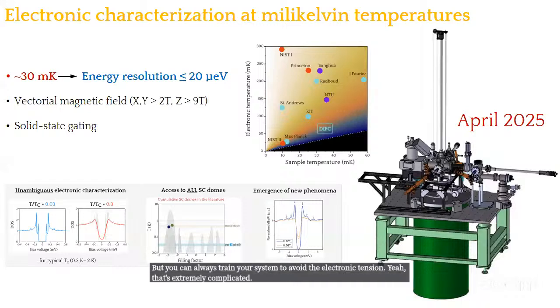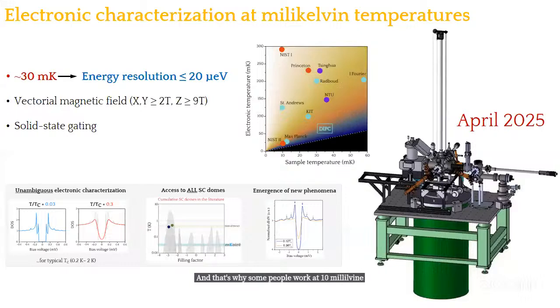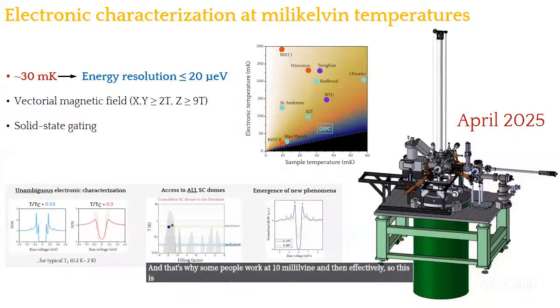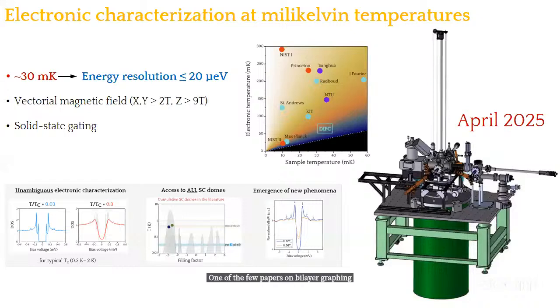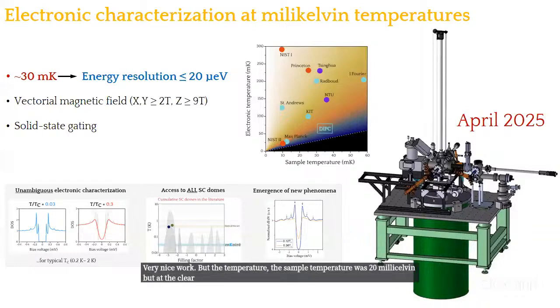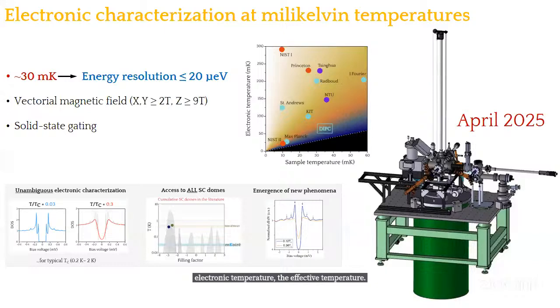And that's why some people work at 10 millikelvin. One of the few papers on bilayer graphene has been done with this system, on superconductivity, which is very nice work. But the sample temperature was 20 millikelvin, while the declared effective electronic temperature is more than 200 millikelvin, so an order of magnitude above that. If you optimize that, you can improve the resolution a lot. But you have to be careful, otherwise it's like working at 2 Kelvin.